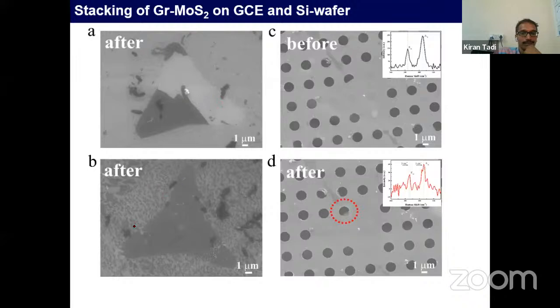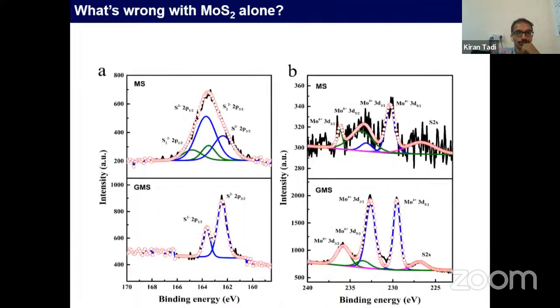But in this case, which is protected with the graphene, the MoS2 is stable enough, and the Raman spectra also shows no shifting in these bands, A1G and E2G. There is no shifting here for the graphene-protected MoS2. So what happened, what's wrong with this MoS2 to know this?